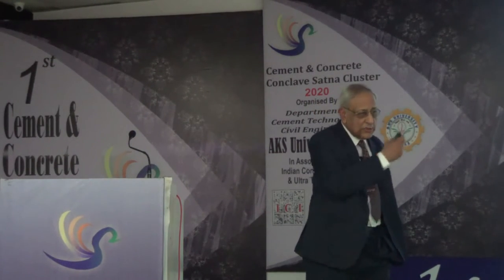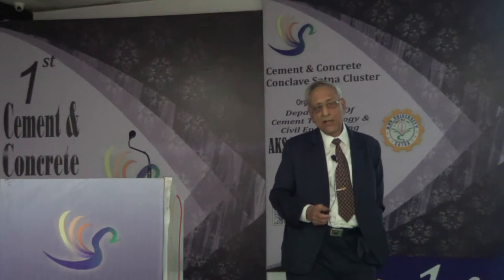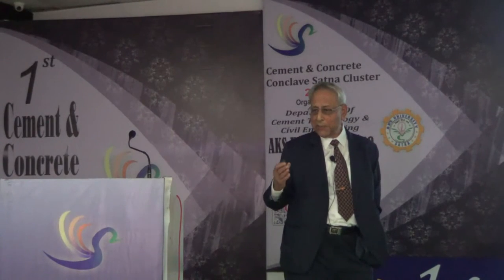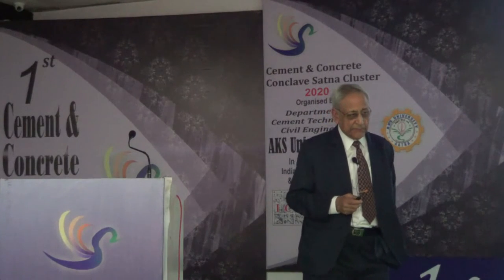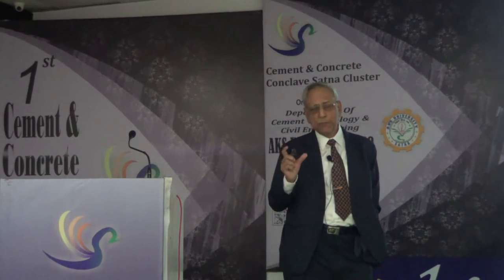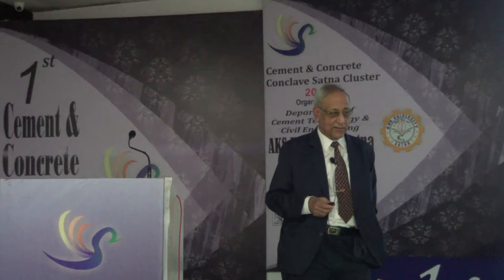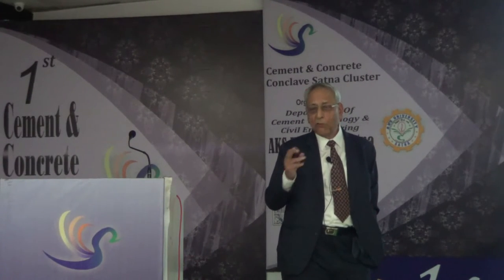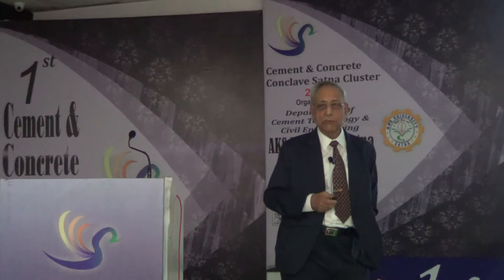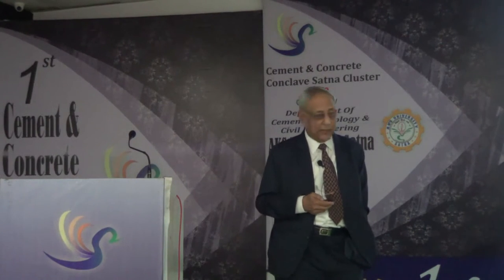Now, taking all these four together, what we have seen is that in reality there are thousands of buildings whose deterioration and damages have been statistically analyzed. Those statistical analyses have shown that materials per se account for only 12% of all the failures. The major failures come from the constructional details where we have not done the right part. And the third is, of course, the environmental and loading aspects, as I have told earlier.